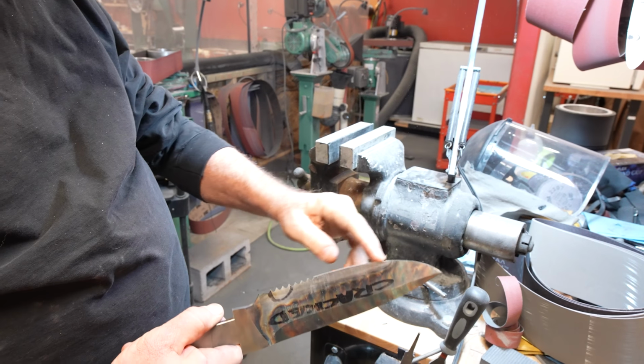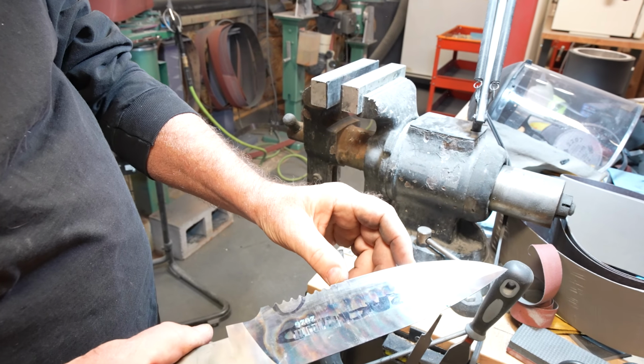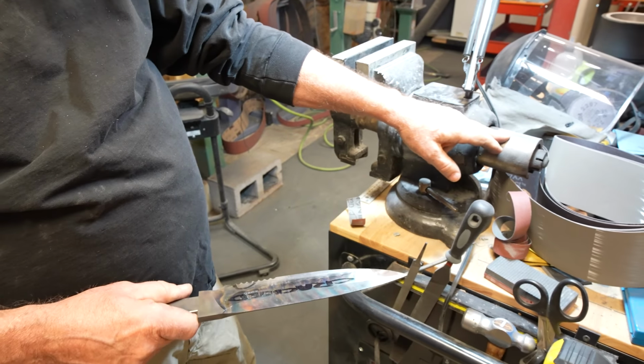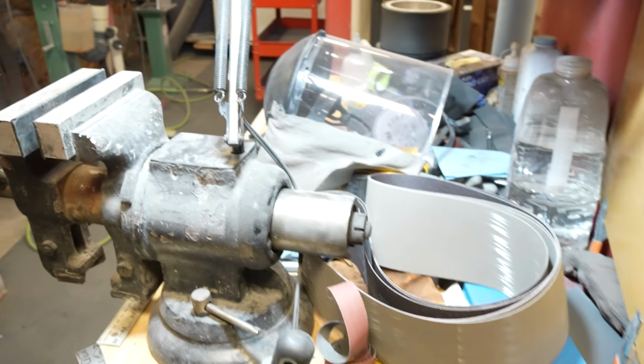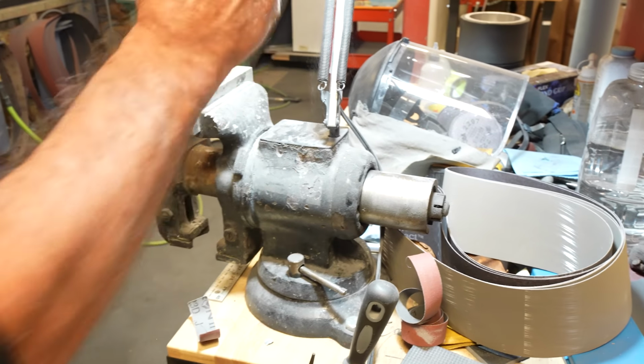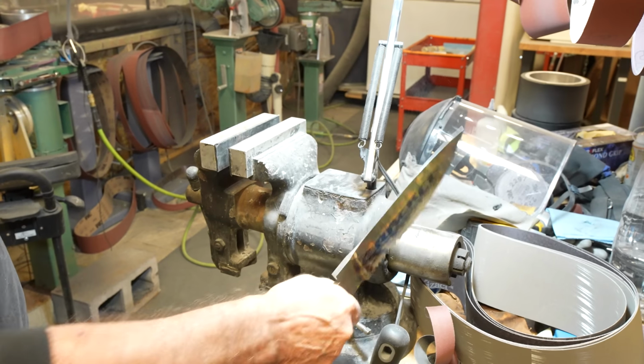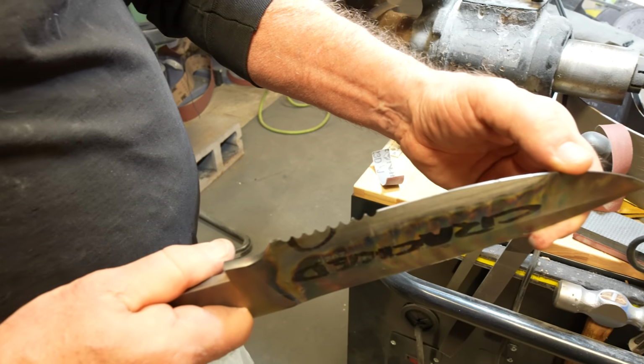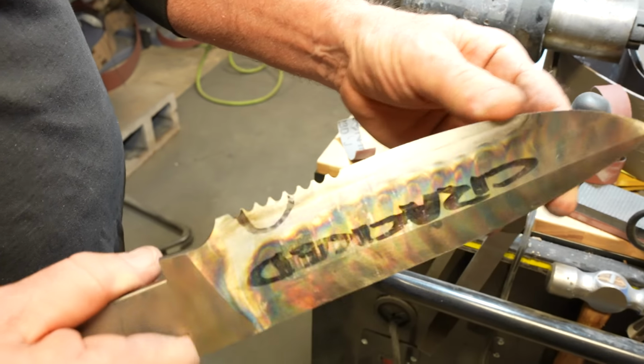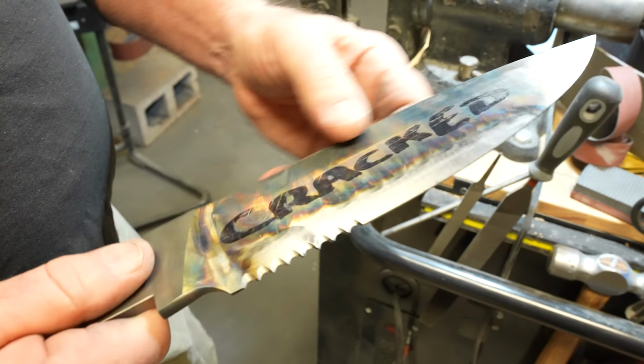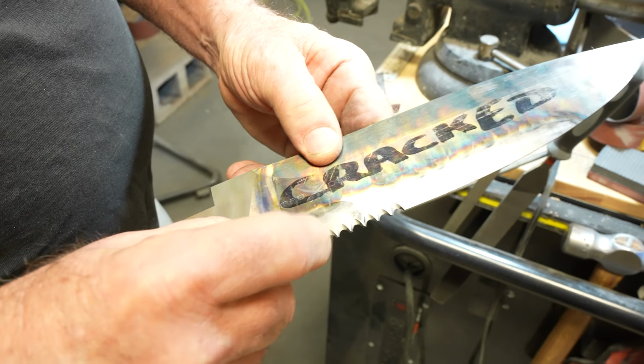I keep it around only so I can show off how tough these knives are, even if they've been damaged. This is 20 thousandths of an inch thick here, and it's 62 Rockwell. This is steel on a vise. I'm taking chunks out of that. See any damage there? No, you don't, because there isn't any. And we've still got the crack in the third tooth there.